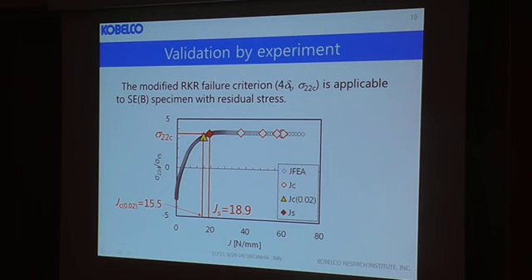JC are compared with the predicted JS, together with the master curve 2% tolerance bound value, as shown in this figure. JC is calculated by EPFEA at fracture load on test. In this figure, we see that the fracture always occurred after σ22 reached σ22c, and the predicted JS was conservative compared with JC and close to the 2% tolerance bound.